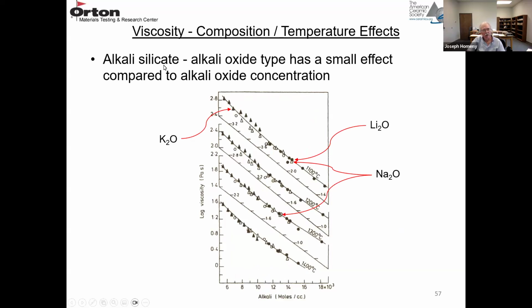So in these alkali silicate glasses, the alkali oxide type really has only a small effect on the viscosity. What has a big effect is the concentration of the oxide. So this is log viscosity against mole percent alkali additions. And there's different temperatures here, 1400, 1300, 1200, and 1100 degrees C. So K2O additions are the solid triangles, Li2O are the solid circles, and then the open triangles are Na2O.